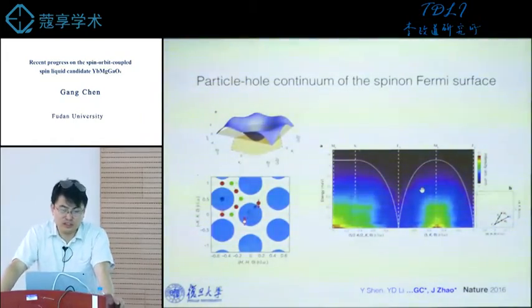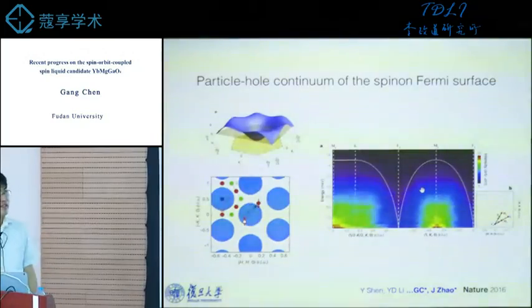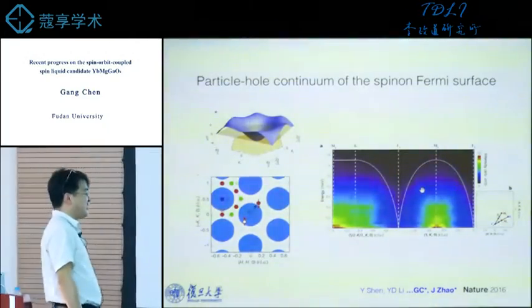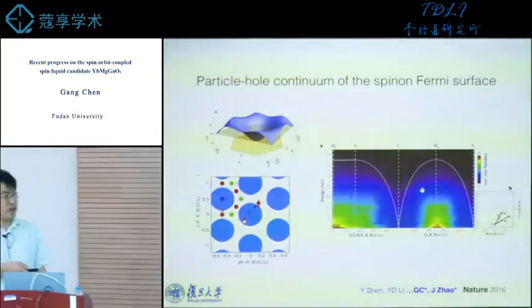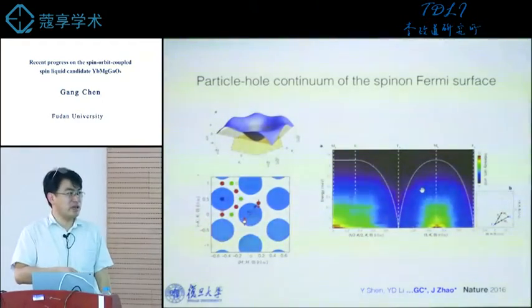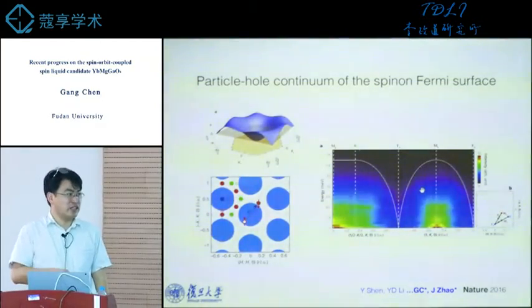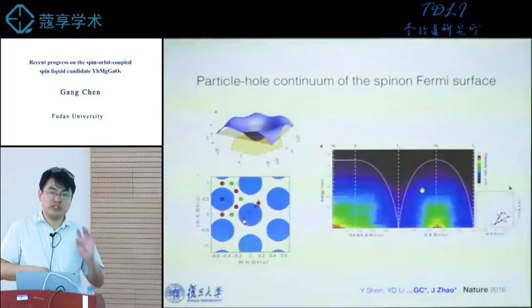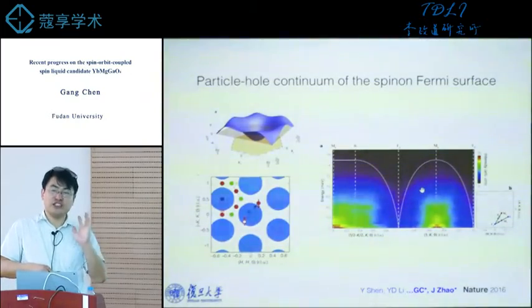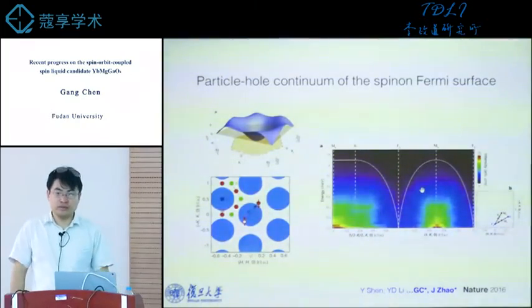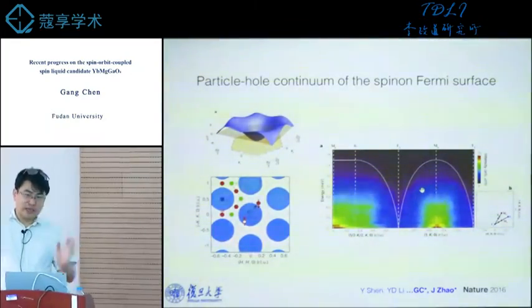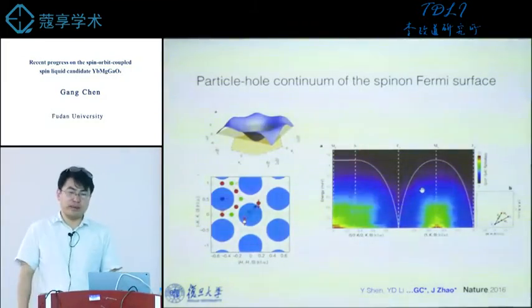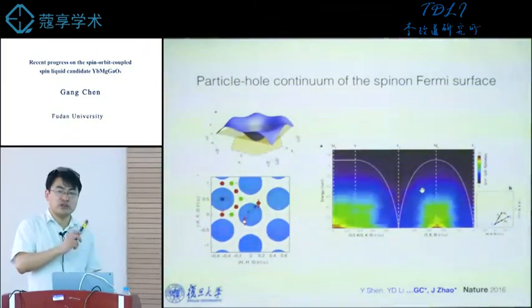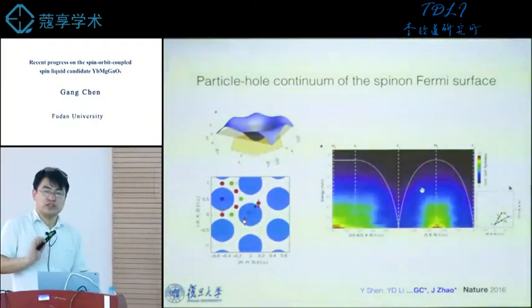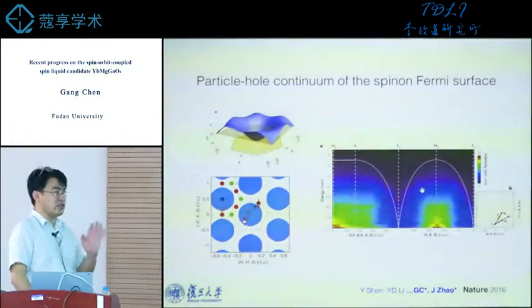No. Because I spin wave to compare the longitude distribution. That's for spin wave theory. So at the low energies, all these gauge fluctuations become very important. You get a divergent density of states. So that means you would get a higher intensity at the low energies. The experiment supports this view. Experiment sees intensity actually goes up at low energies. So this is consistent with the theoretical suggestion.